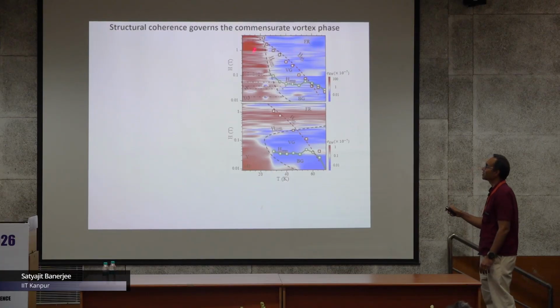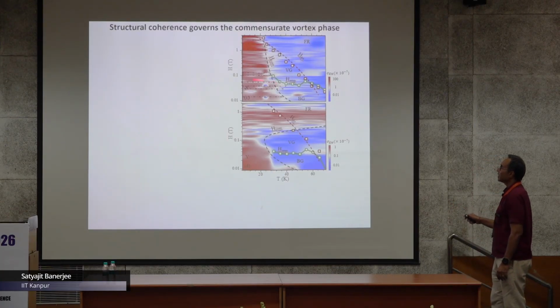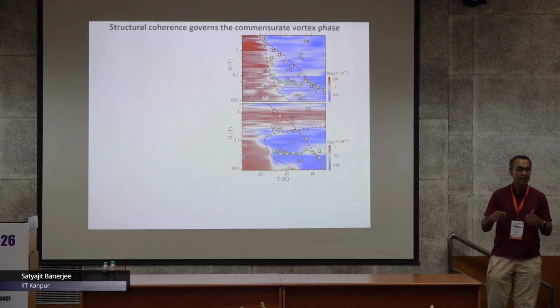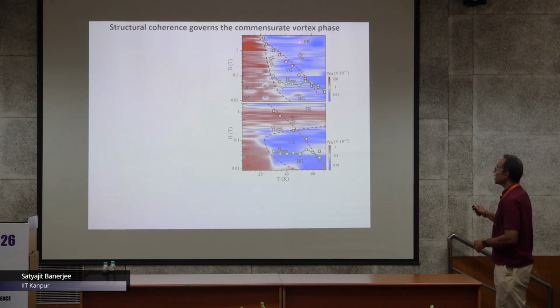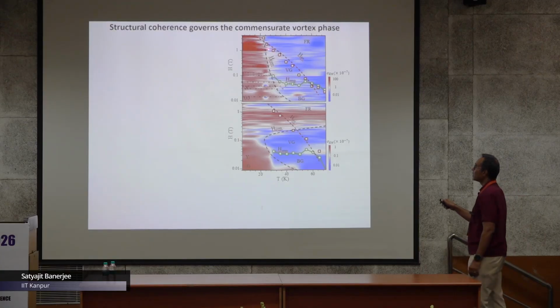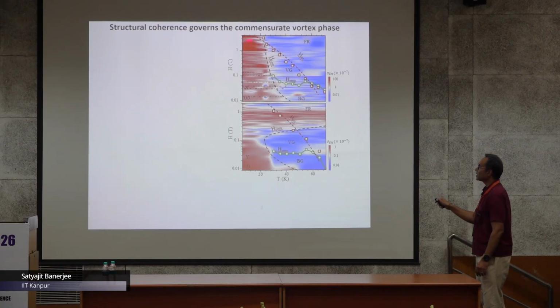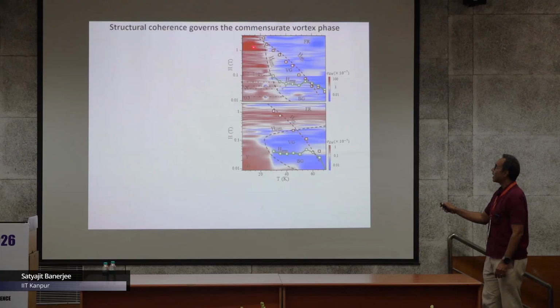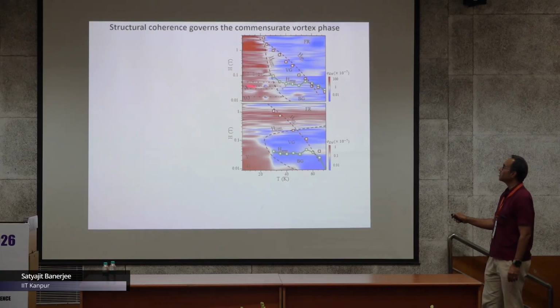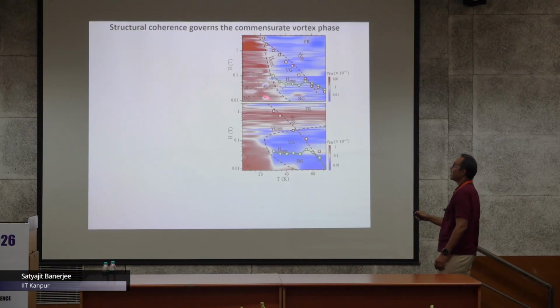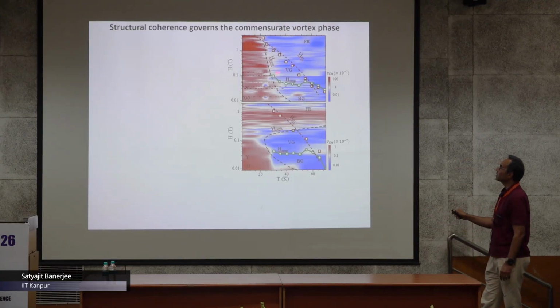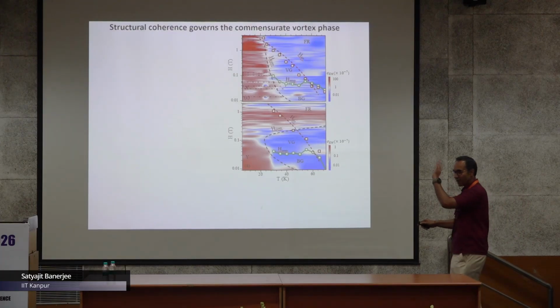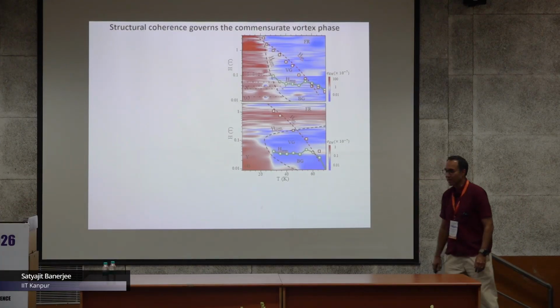You can see in this phase diagram, this line is where thermal fluctuations dominate inside the crystal and destroy any sort of pinning in the sample. The entire region below this line is the vortex solid phase, and these black lines show the intrinsic commensurate states being generated inside the crystal. These intrinsic commensurate states populate the vortex solid phase, but they don't enter into the fluctuation regime above this line.